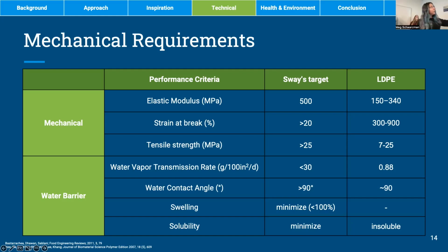Elastic modulus, strain at the break, and tensile strength all directly relate to the durability of the packaging. And then the water barrier metrics are all vital to the material maintaining that aforementioned mechanical integrity, as well as serving as an important protection for anything contained inside the mailer. The water vapor transmission rate is our most important water barrier benchmark that we considered, and it's defined as the rate at which water vapor permeates through a film at set conditions of temperature and relative humidity.